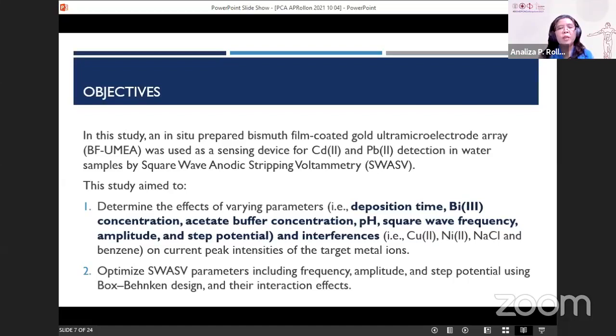In this study, we have in situ prepared the bismuth film coated gold ultra microelectrode array, which means that we deposited the bismuth into the gold ultra microelectrode array. And we use it as a sensing device for cadmium and lead detection in water. The study used square wave anodic stripping voltammetry. And we determined the effects of various parameters like the deposition time of the bismuth and the concentration of the bismuth and the acetate buffer concentration, the pH, the square wave frequency, amplitude, and step potential.